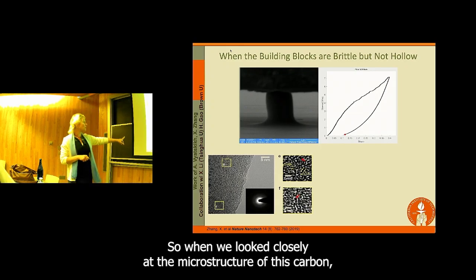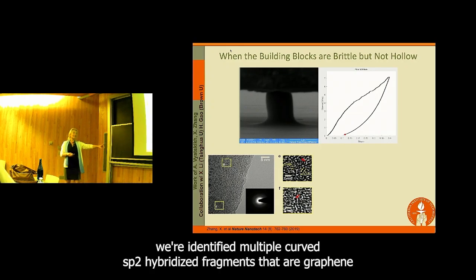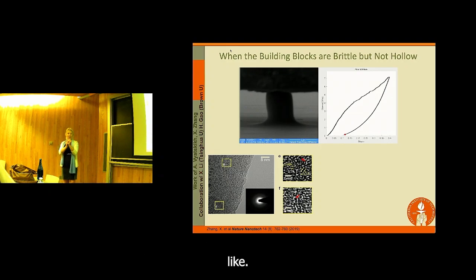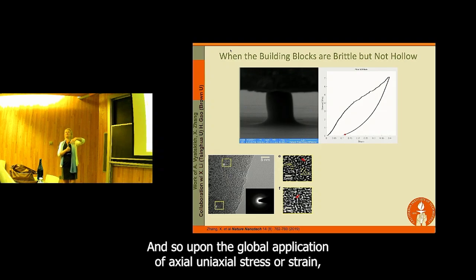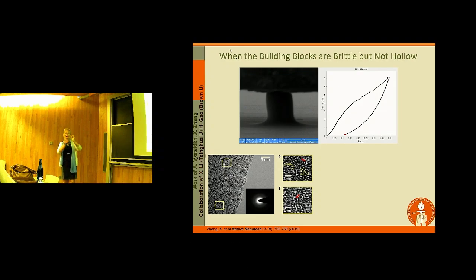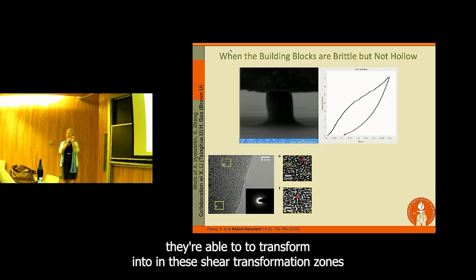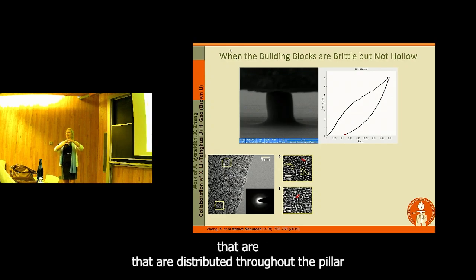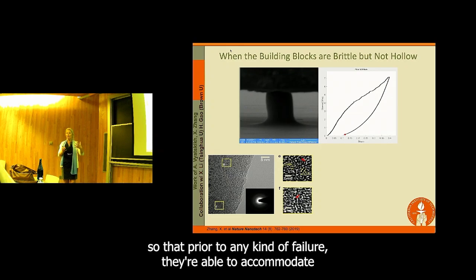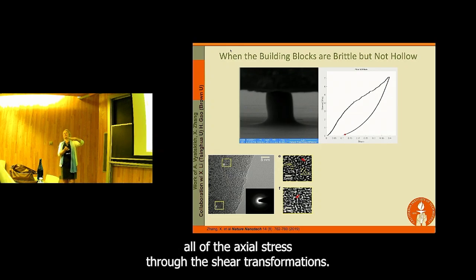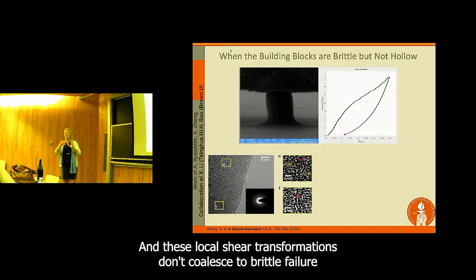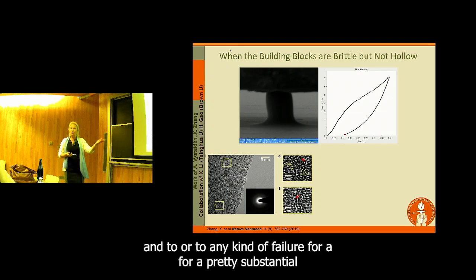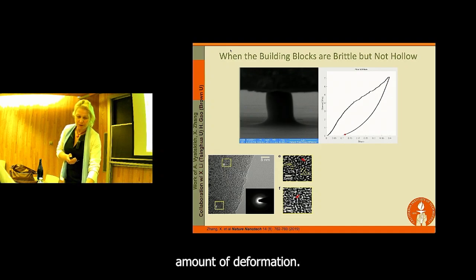When we looked closely at the microstructure of this carbon, we identified multiple curved sp2 hybridized fragments that are graphene-like. Upon the global application of uniaxial stress or strain, they're able to transform in shear transformation zones that are distributed throughout the pillar, so that prior to any kind of failure, they're able to accommodate all of the axial stress through the shear transformations. And these local shear transformations don't coalesce to brittle failure or to any kind of failure for a pretty substantial amount of deformation.